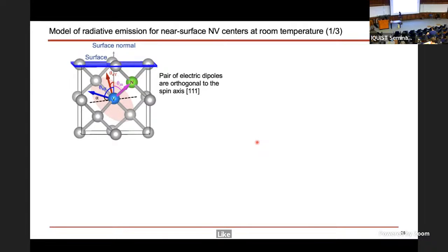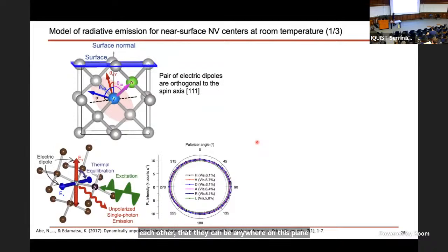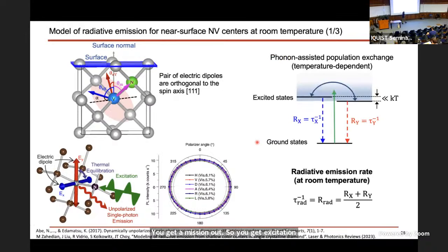In the case of diamond, the NV center arises from a pair of electric dipoles, which I've labeled X and Y here. You can think of the dipoles as moving and emitting light, and it has to be perpendicular to the spin axis. But these dipoles also have to be perpendicular to each other, so they can be anywhere on this plane. When you excite these dipole moments, you get emission out. And what the picture looks like is the following. It's a highly temperature-dependent behavior.